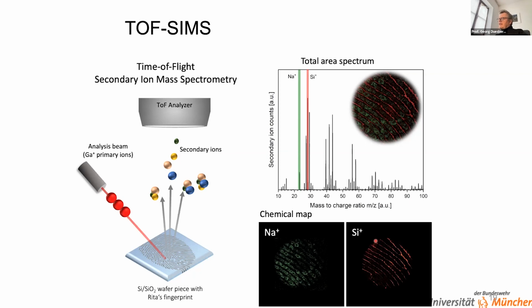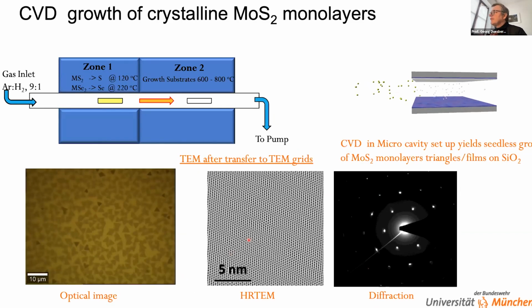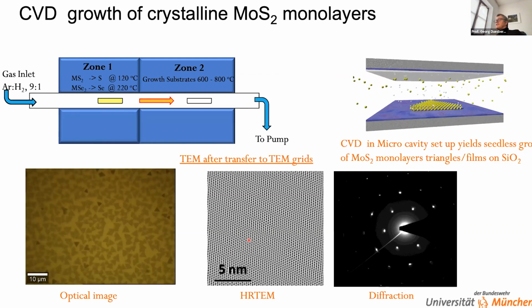But joke aside, you can tune this process, especially using different anodes that are super surface sensitive. And this is what we've been doing on 2D materials. I said that I wanted to investigate the contaminations on 2D materials, but we use not graphene for this, but MoS2. The simple reason is the contaminations are usually carbon-based, and to investigate carbon on carbon is not so useful. So that shows up better on MoS2, but in principle we believe that the very same things happen on graphene, as I will show you later on.